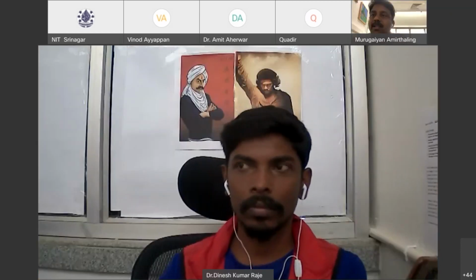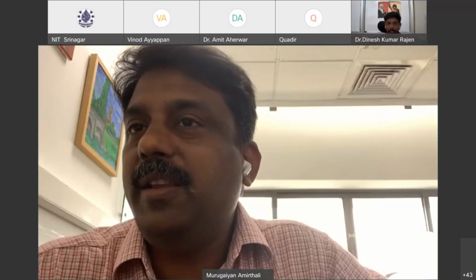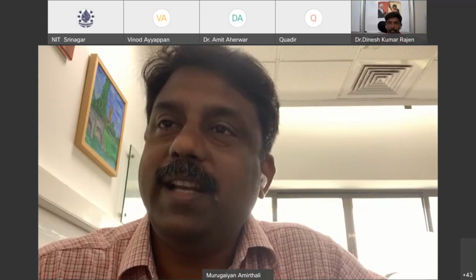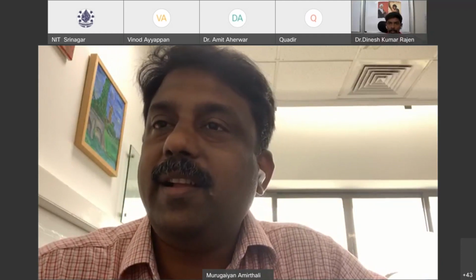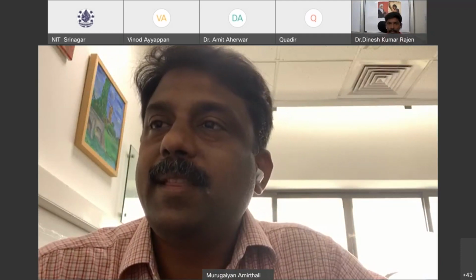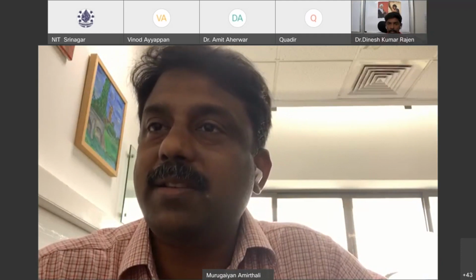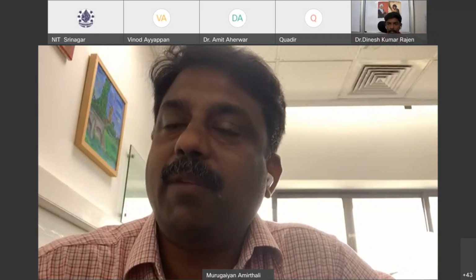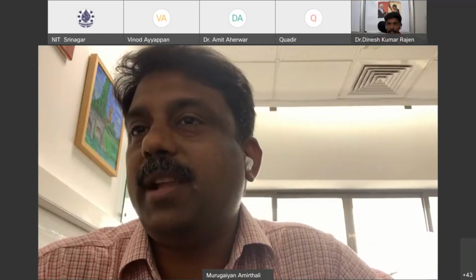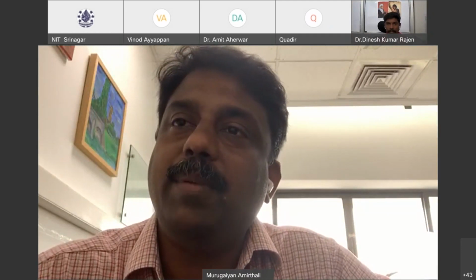Actually, sir, I am trying to do metal additive manufacturing of nickel titanium alloy for shape memory alloys. Thermally, I am trying to control any sort of distortion, because I'm still in a literature study. See the distortion. You need to first understand how the thermal boundary conditions evolve, isn't it? You can also control the preheating or the interpass temperatures. That will also change how the distortion evolves because you're locally changing the thermal profile. That is one strategy. The substrate can be preheated. That is now widely adopted in most equipment.